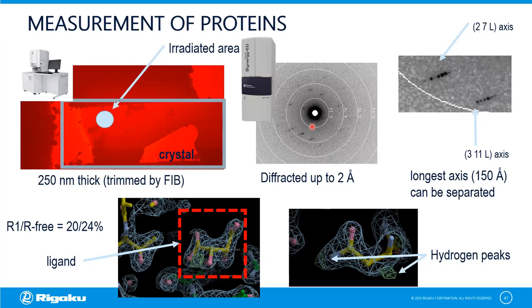The Synergy-ED can actually achieve a virtual crystal detector distance on the order of 2100 millimeters. So there's still some room in there for longer unit cells. The data was collected and refined to a really respectable R1 of 20% with an R-free of 24%. We can see the tartrate ligand in the map, and we can even see hydrogen peaks in the map.